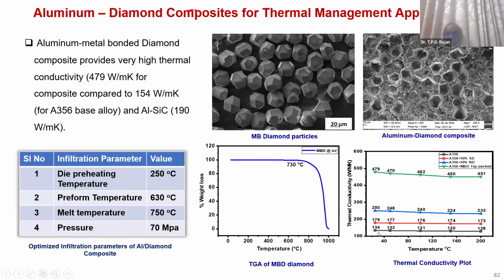That means the alloy is 134, and by infiltration we can see that the thermal conductivity is enhanced up to almost 479 watts per meter Kelvin.